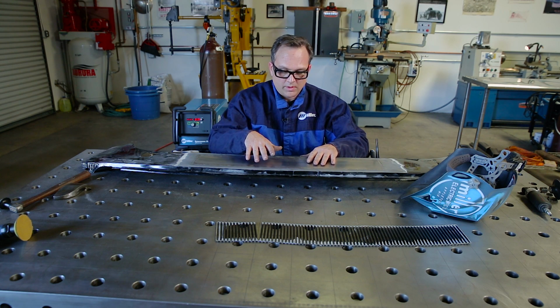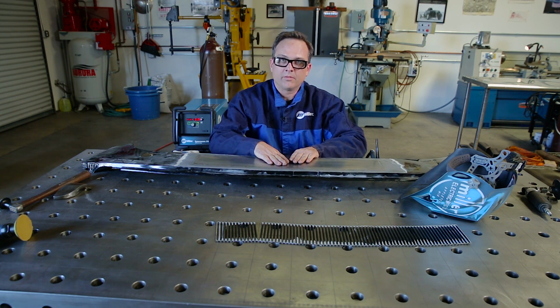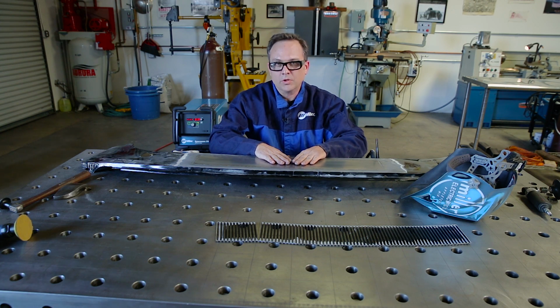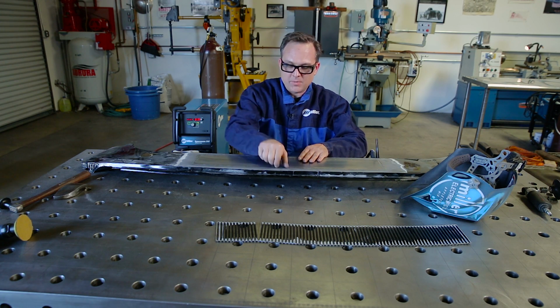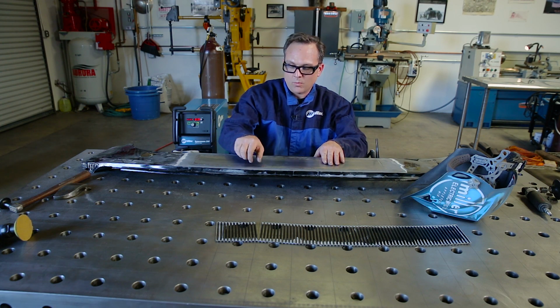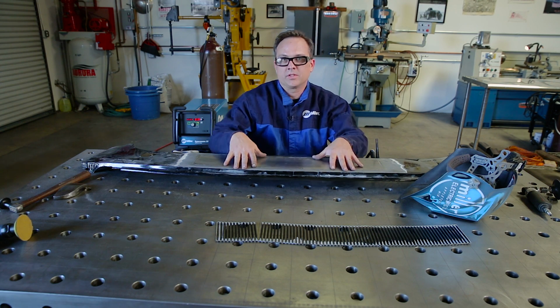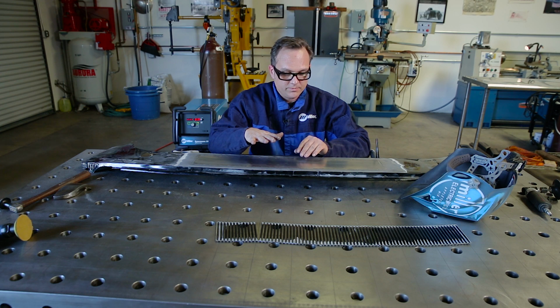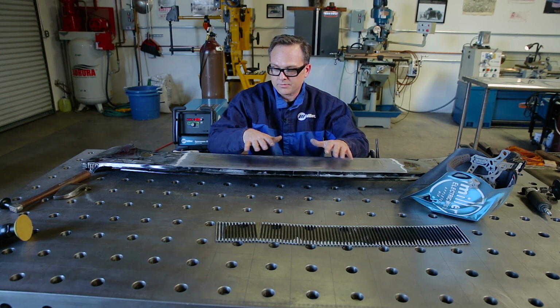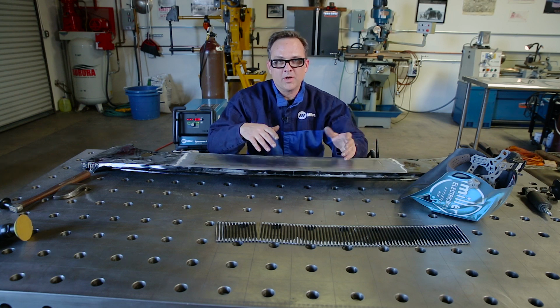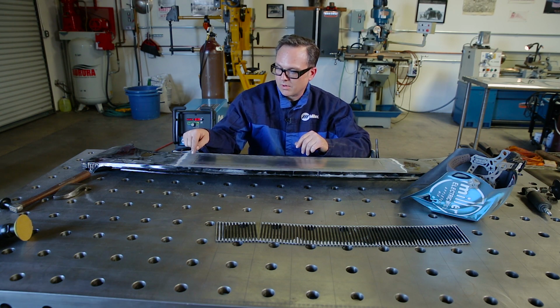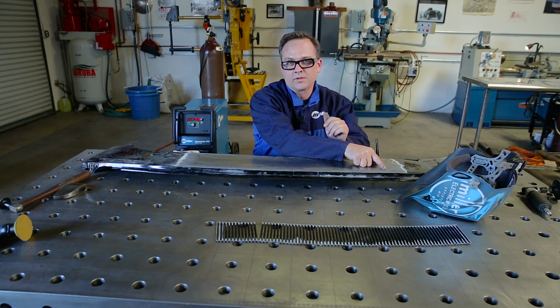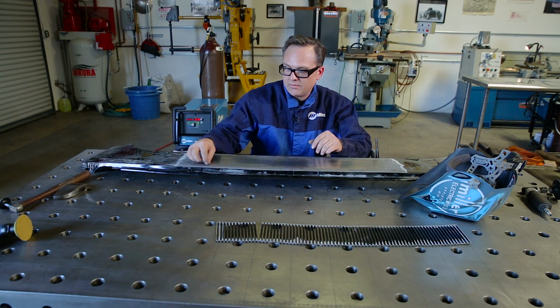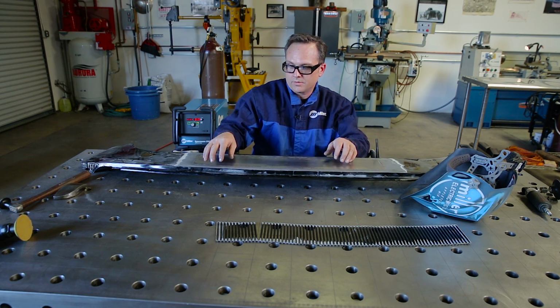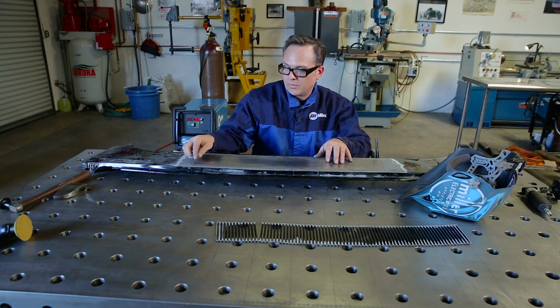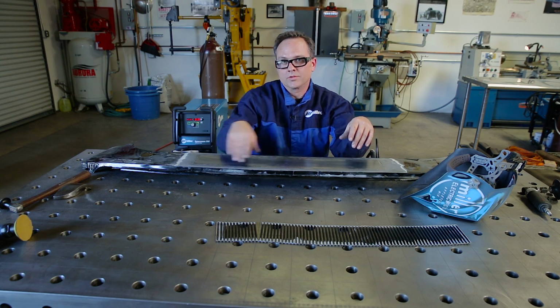And I know I've seen in a lot of instructional videos and books, people talk about skipping around and welding different sections, like 1-inch sections in different places to keep the heat down. Something that's my preference, and as time has gone on and I've gotten much better at what I do, I've learned if I start at one end and go all the way to the other without stopping, that it creates an even heat all the way across, and you're not skipping back and forth. And with that even heat, you get even shrinkage across the whole part.